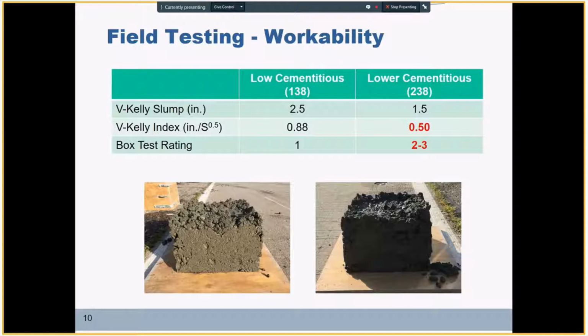But when testing this concrete with lower cementitious material, 238 pounds, the box rating numbers increased a little. We had numbers of 2 or 3, which corresponds to about 30-40% of void on surface of the boxed sample, as we can see on the picture on the right side. The Kelly index was 0.5, which is a bit less than what we'd like to see as a Kelly number for a good paving concrete.